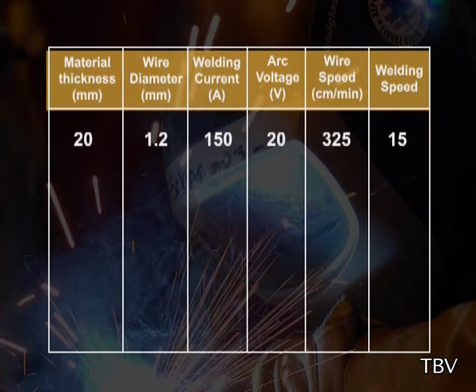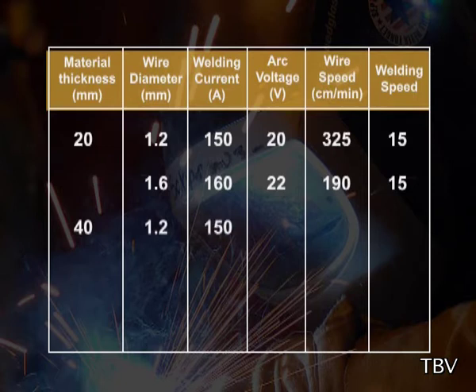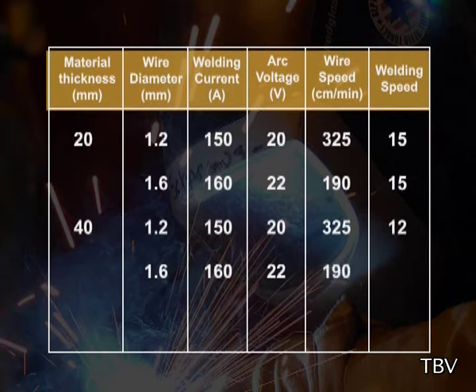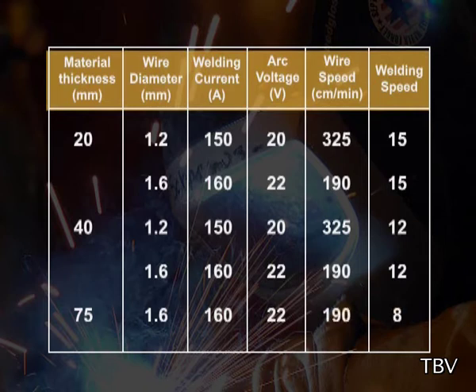welding speed 15. For material thickness 20 mm, wire diameter 1.6, welding current 160, arc voltage 22, wire speed 190, welding speed 15. For material thickness 40 mm, wire diameter 1.2, welding current 150, arc voltage 20, wire speed 325, welding speed 12. For material thickness 40 mm, wire diameter 1.6, welding current 160, arc voltage 22, wire speed 190, welding speed 12. For material thickness 75 mm, wire diameter 1.6, welding current 160, arc voltage 22, wire speed 190, welding speed 8.